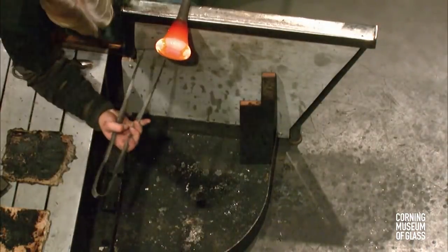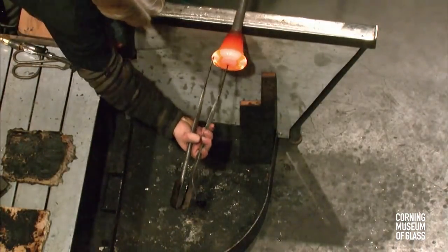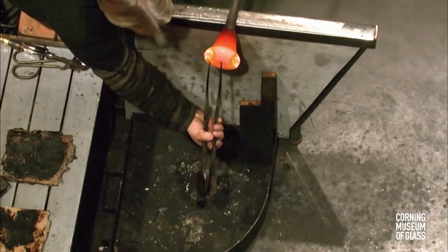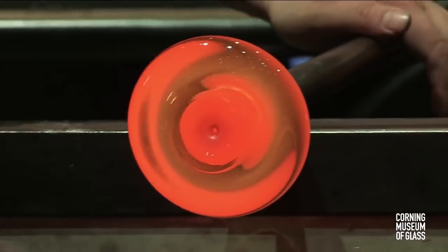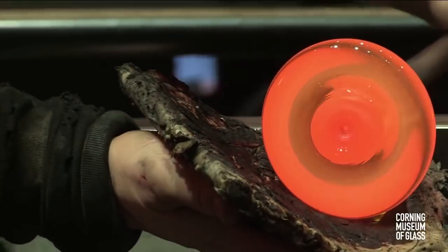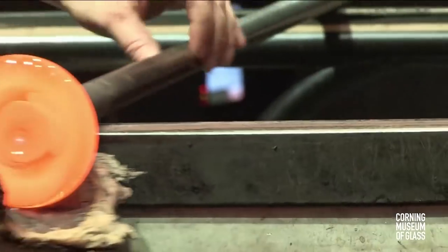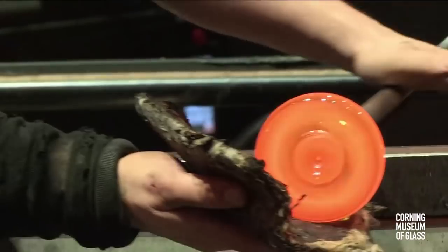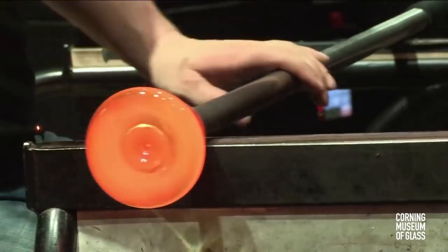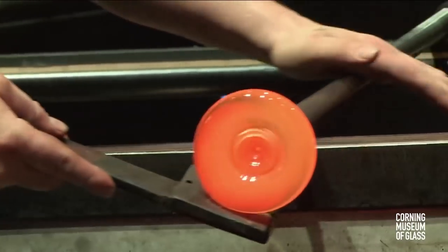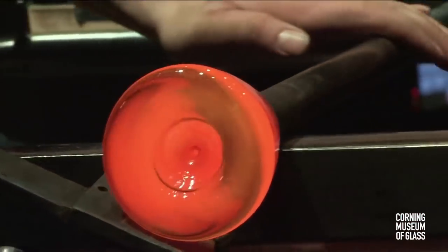Yeah, so there was a question online about how the piece maintains its shape when it's cooling down. When we put that piece in the annealing oven, if you were watching here online, you saw that it was still glowing orange. That's really because it's so massive. That piece was, who knows, probably 3 inches thick or more, the wall thickness. So it was glowing orange in the annealer. Even though it was glowing orange, that was mostly in the core, the glass was cool enough that it won't lose its shape at all in the annealer. So the trick to keeping glass from deforming in the annealer is to put it in there at the right temperature. You can't put it in there too hot.